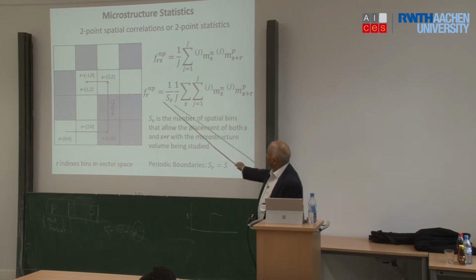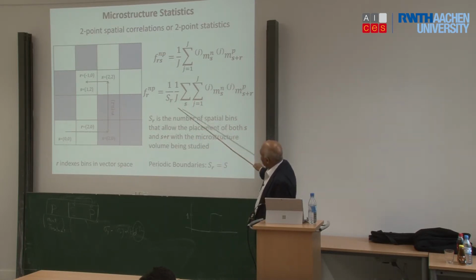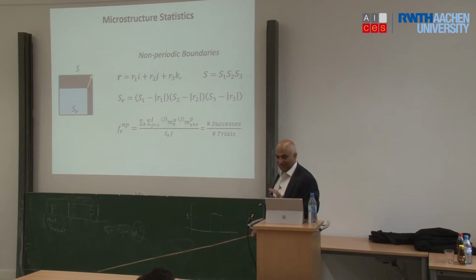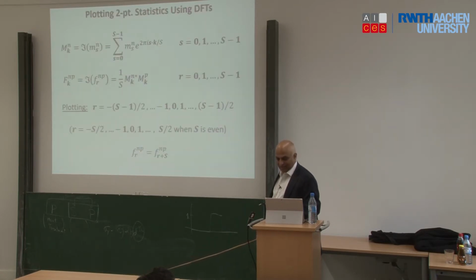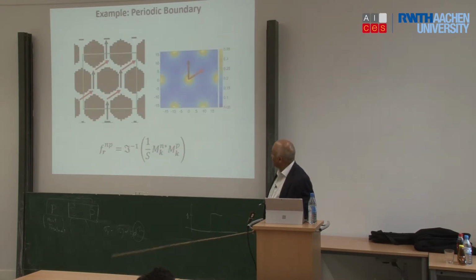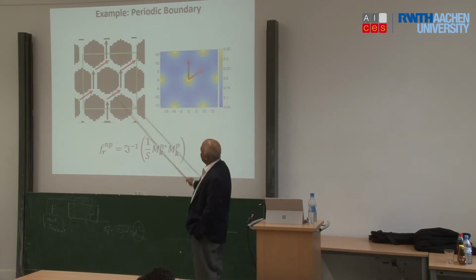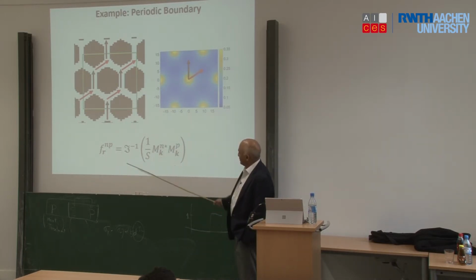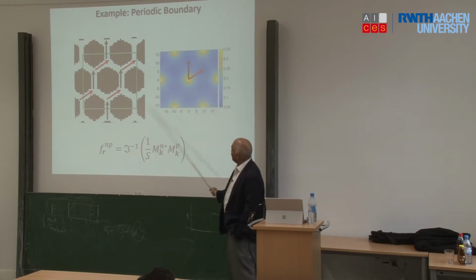Okay? So essentially, to compute this, if you do this in the DFT space, then this summation goes away. And that's a big summation, right? Because you're doing it over every voxel. If you have 150 million, that summation simply disappears. And it's the exact result. This is not an approximate result, this is an exact result, and you'll get exactly the same answer if you do it by DFTs. So essentially what we do is take the microstructure, convert it to DFTs, do the operation, and do an inverse. And after you do the inverse, that's what it looks like.